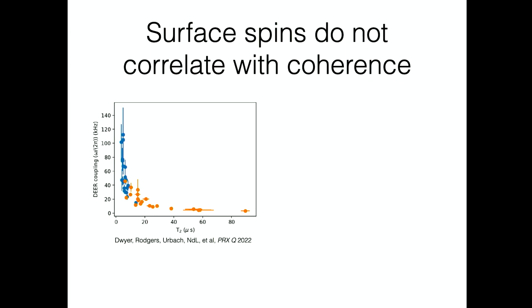And you can do things like take a lot of data where you look at different NV centers and plot, for example, the DEER coupling versus the coherence time. And this looks like a pretty darn good correlation, right? So this looks like a little bit of a smoking gun, that as the DEER coupling goes up, my T2s go down. And similarly, as my T2s go up, my DEER coupling goes down.